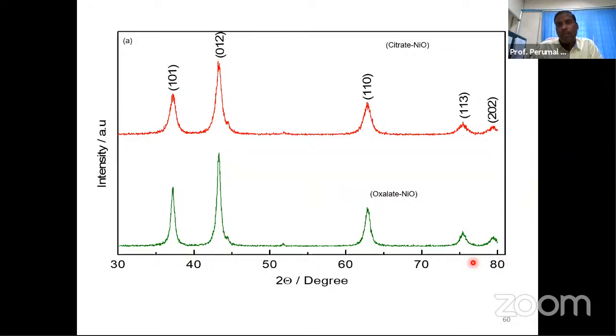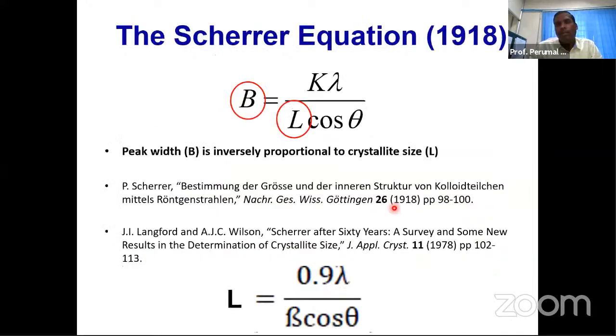So you can quantify how much the crystallite size is. For example, in this case, nickel oxide synthesized by some method using citrate or oxalate as a chelating agent. You can quantify the crystallite size using this standard equation known as the Scherrer equation. The crystallite size L at some particular HKL is equal to 0.9 lambda divided by beta cos theta. 0.9 is a constant, known as the Scherrer constant. It varies from 0.6 to 0.9, maximum is 0.9. Lambda is the X-ray wavelength, beta is the full width at half maximum, and theta is the diffraction angle.